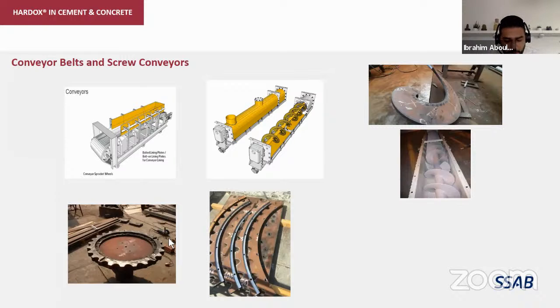Then we have the screw conveyors, and they are usually moving the granular parts and handling the bulk material. They are typically mounted right on top of the hopper, or sometimes if it's a silo, that will be storing and so on. And for that, we recommend using Hardox 500 tough or 500 in the screw blades, on the second picture from the right. So in the screw blades, we recommend 500 or 500 tough. In the trough and tubes, you can also use Hardox 450, 500 or 500 tough, which will extend the service life of your screw conveyor.